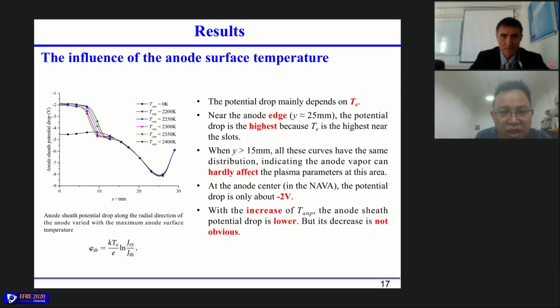And when y is larger than 15 millimeter, all these curves have the same distribution, indicating that the anode vapor can hardly affect the plasma parameters in this region. At the anode center, the potential drop is only about -2 volt. And with the increase of the anode temperature, the anode sheath potential drop is lower, but its decrease is not very obvious.